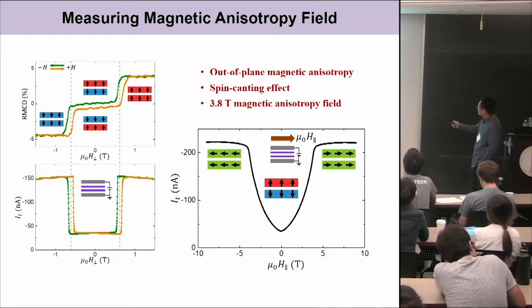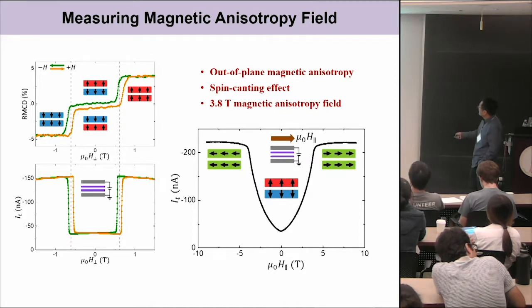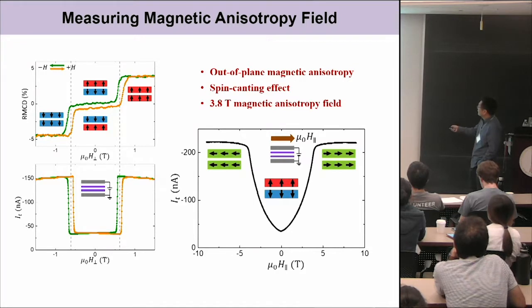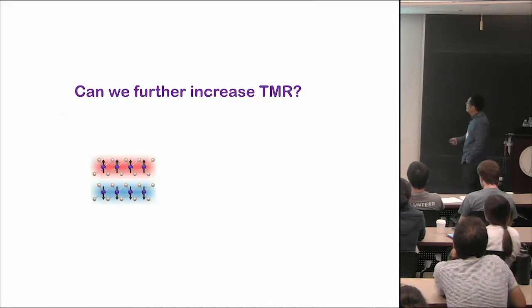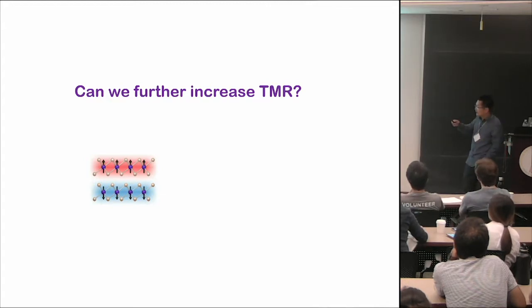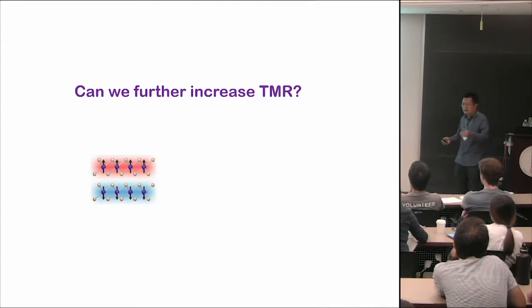I'm going to ignore these slides. This basically shows we can apply an in-plane magnetic field to see these spin canting effects and to measure this anisotropic field, which is about 3.8 Tesla. We can further increase the TMR by increasing the layer number. This is what's nice about the spin filter concept, because you can artificially add functions to these spin filters in the middle.